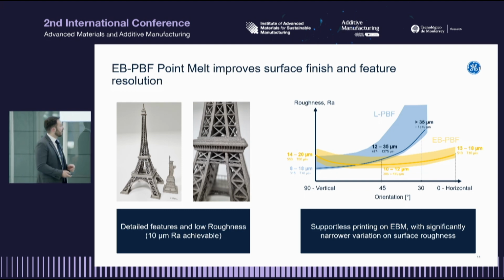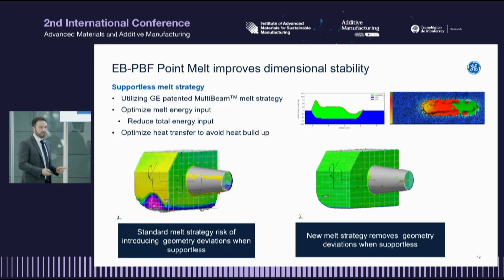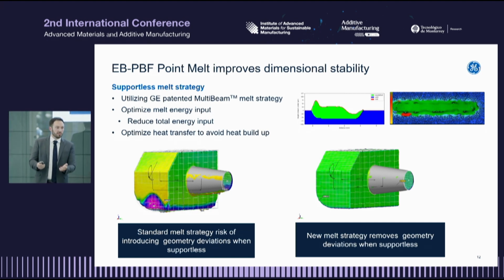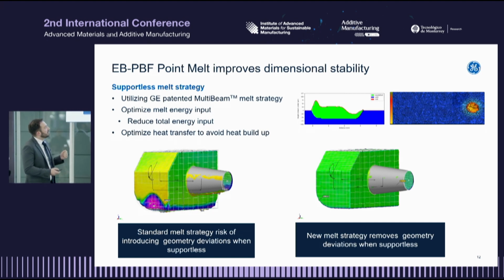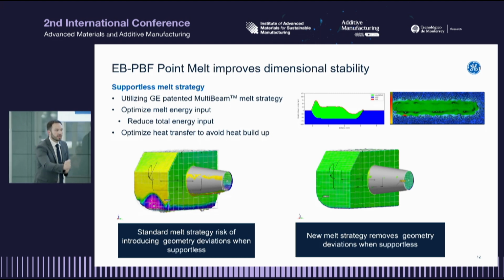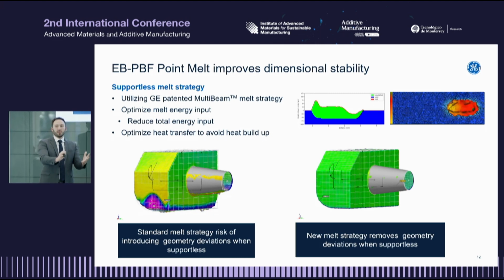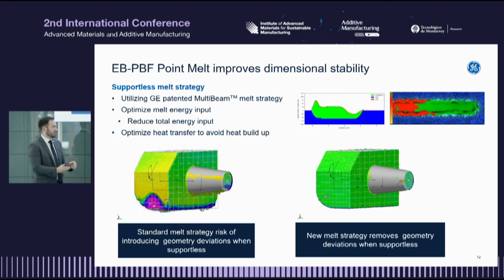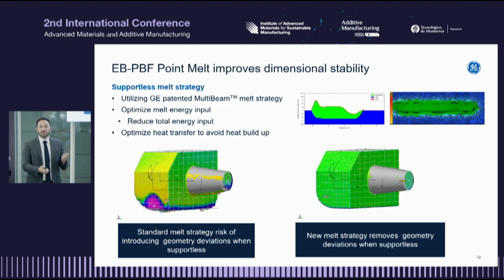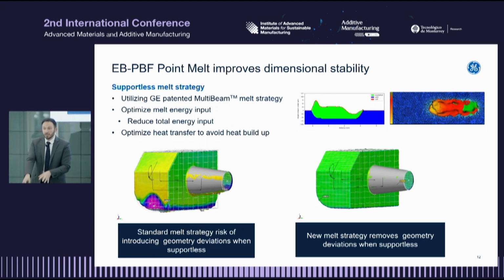We know how to, in laser space, print really low angles, and it involves slowing the machine way, way, way down to the point of not being productive anymore. I've made my business case even worse. With the electron beam technology and this new point melt, I can actually print purely supportless and have no need for those mechanical supports to a build plate whatsoever. The reason that you need supports is shown in the upper right-hand side with line melting. If you have a line pushing across that powder bed, I'm making a plow of powder. I'm physically moving the powder with the energy source. Because now I don't have a vector involved, my only direction of energy is down, I don't actually need those supports to tie that part into the powder bed.